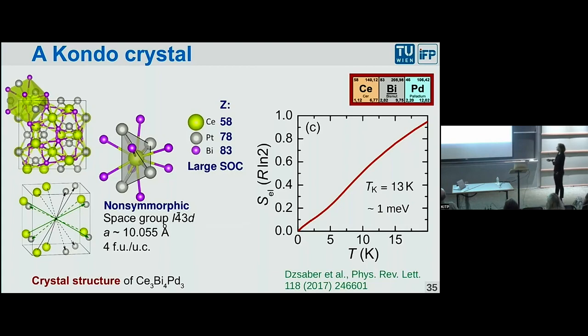And one way to do that is to measure the specific heat. The specific heat measures how many degrees of freedom you have at low energy. And that tells us that the energy that is now relevant for the system is about 10 Kelvin, which corresponds to 1 millielectron volt, even though the typical bandwidth of a non-interacting system is an electron volt. We have now a very small effective energy scale, as if our Fermi energy was decreased by three orders of magnitude. Or you can see it in other words: the band was very wide, one electron volt wide, and now we push it all together to one milli-electron volt, and then many, many are at the same energy.